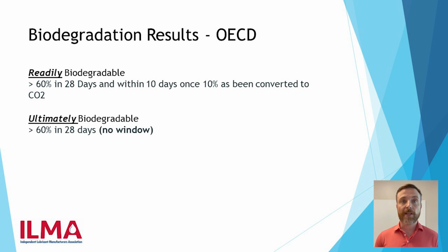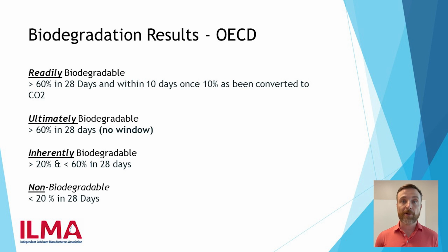Ultimately drops the 10-day window requirement and just requires 60% degradation in 28 days. Inherently is any value between 20 and 60% in 28 days. And finally, non-biodegradable is less than 20%.